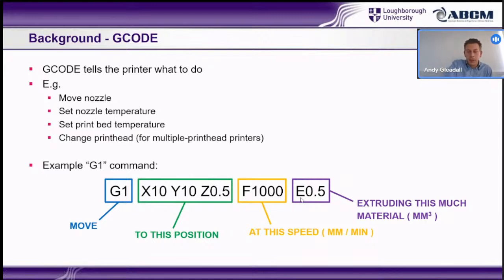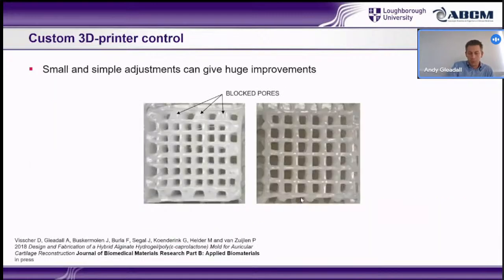You can write this by hand to do relatively simple things, but it gets a bit painful for more complicated ones. For this type of structure, we had this issue of blocked pores at the top, where it was critical that we didn't have blocked pores because we were growing cells in here. The G-code for these 5 lines is very simple. We just need to go to a certain Y value, a certain X, certain Y, certain X, and so forth. And it was the G-code that was causing the problem. It wasn't the printer's fault. It was the print path.